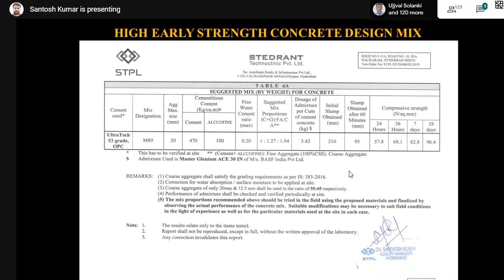People are expecting high early strength for precast structures. See, you can see this is M80 grade of concrete with 470 cement. We have deviated from the standard because the designer is not from India. He doesn't want to restrict cement content to 450. So based on the customer request, we have used cement content of 470. And Alcofine we have used 100.